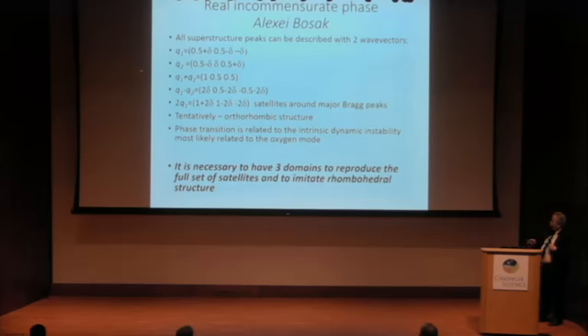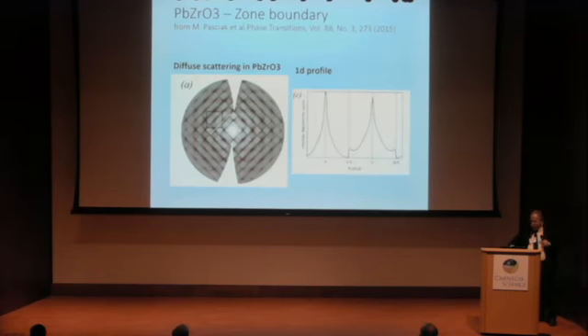Now we can have second order satellites near the endpoint, and in reality we should have second order satellites near the major Bragg peaks, which we do indeed see. But now, about the possible origin of this. There was an excellent paper of Marek Pasiak that Irka already referred to briefly, where it was demonstrated that